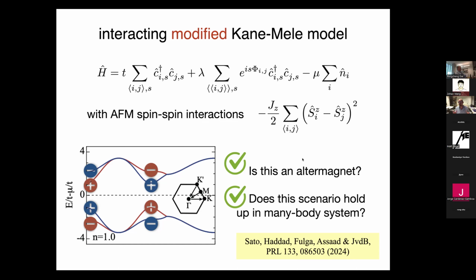So the good part is that if you manage to get the spin along an arbitrary direction, there will always be some anomalous Hall effect. Well, I mean, according to your theory, even in the case of no spin-orbit coupling, you would still expect a little bit of ferromagnetism, right? Basically, associated with time reversal symmetry breaking. Yeah.